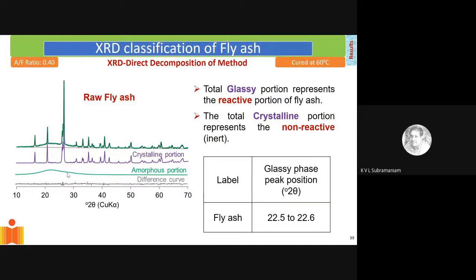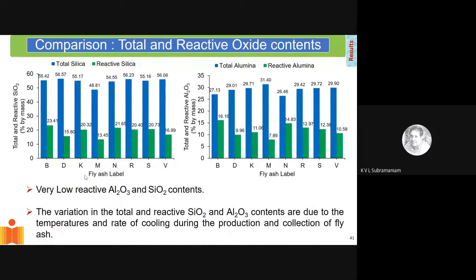So I have to learn to separate out the amorphous form from the crystalline forms, and that is what we did here. For the same fly ashes, in these two graphs, if you focus on the graph on the left-hand side, you will see the total silicon oxide, SiO2, that is present, the total silica present in the material. The blue lines show the total SiO2 present in the fly ash. The green lines show the SiO2 that is present in the reactive form. What is the difference? The difference is the SiO2 that is present in the non-reactive form of quartz, and that doesn't enter into the reaction. It is the green bars that are the form of silica that enter into reaction.